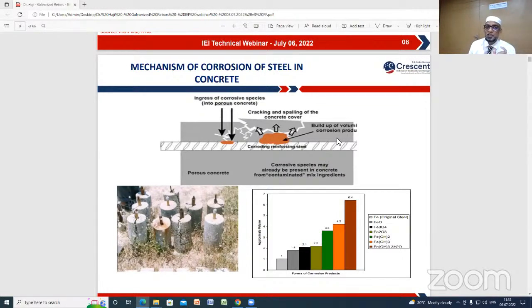The original diameter is reduced, but there is an increase in volume around the steel rebar. Once there is an adequate increase in volume, it will offer pressure to the surrounding concrete. That is what we are seeing as spalling and delamination in day-to-day life. If you visit 10 houses, in 2-3 houses, you can easily see the delamination or cracking or spalling.